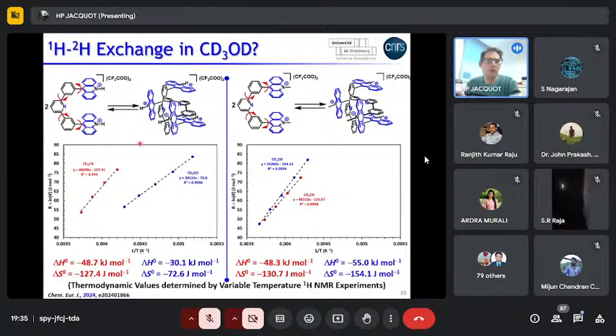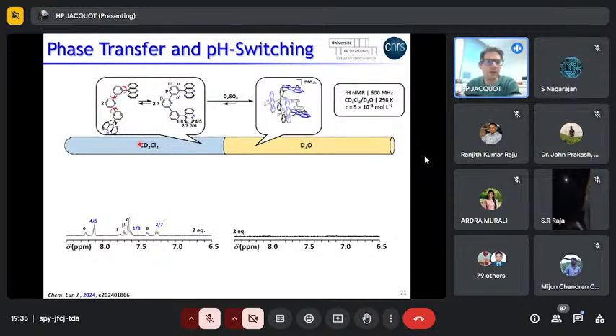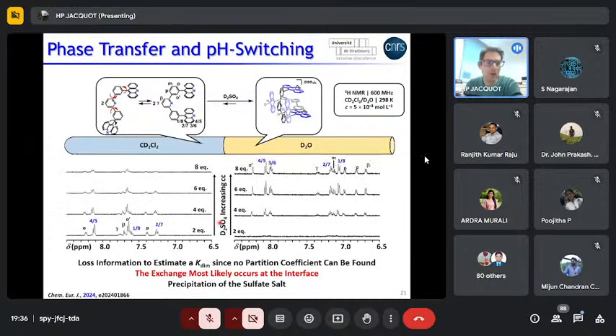We also wanted to trigger the dimer formation by different switches. So one of them was done by protonation, actually very simple, but we did a biphasic NMR experiment. So in the same NMR tube, you have two phases. The bottom layer was DCM and the top layer was water. And you can probe what you have in these two phases. So initially, for the bisacridine derivative, we have only the molecule in DCM and nothing in water. And then when you increase the amount of sulfuric acid in the tube, what you see is that you have a decrease of the precursor in dichloromethane and an increase of the dimer in D2O.